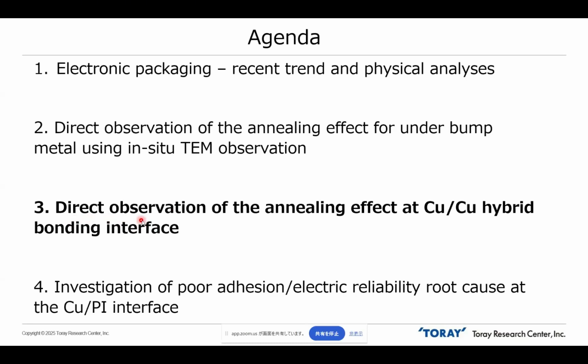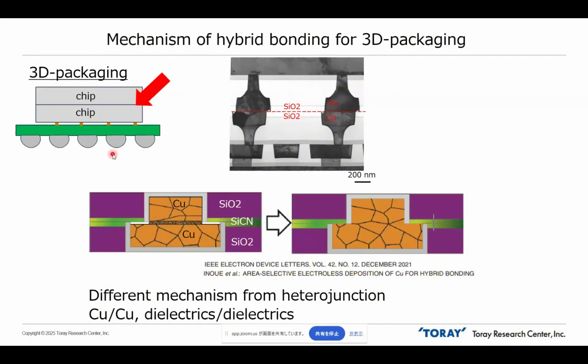The next topic is direct observation of the Cu-Cu hybrid bonding interface. As I explained before, bumpless three-dimensional packaging uses hybrid bonding. Many researchers predict that the initial state of the Cu surface consists of nanocrystals. Then after heating, the crystal grain size of the nanocrystals becomes larger and larger, and they diffuse into each side. Finally, Cu and Cu are tightly bonded. But nobody has seen this kind of phenomenon in real time. So here, we also like to propose our in-situ TEM measurement techniques to understand the Cu-Cu hybrid bonding mechanism.